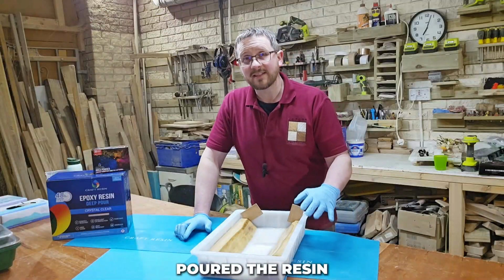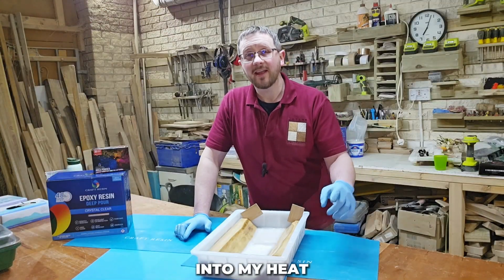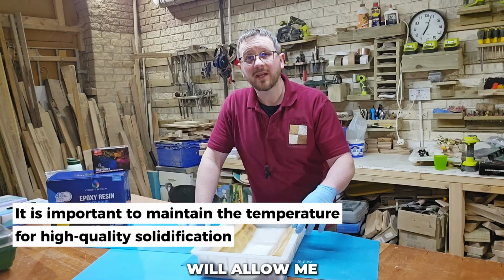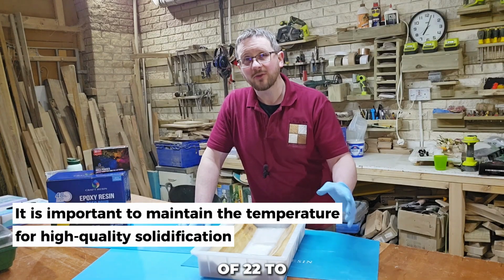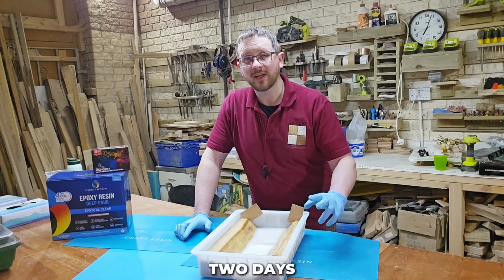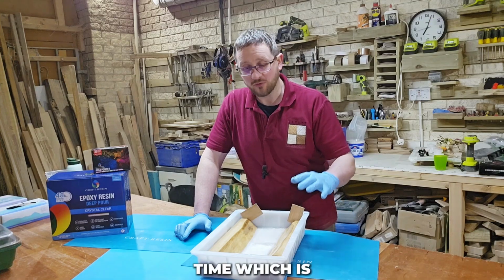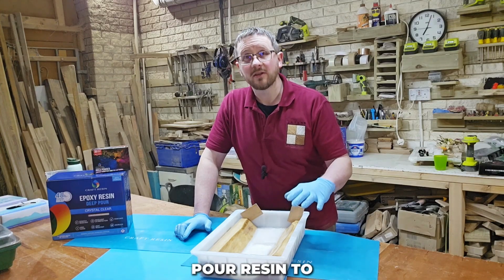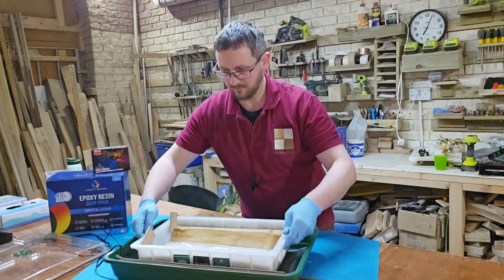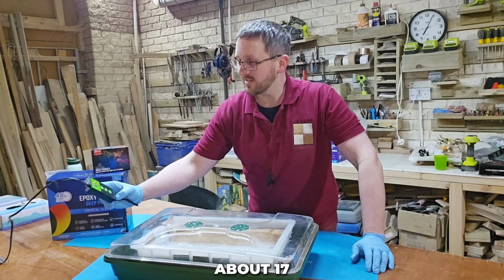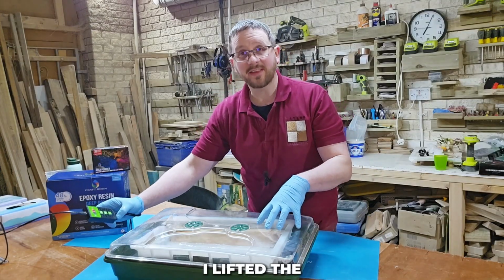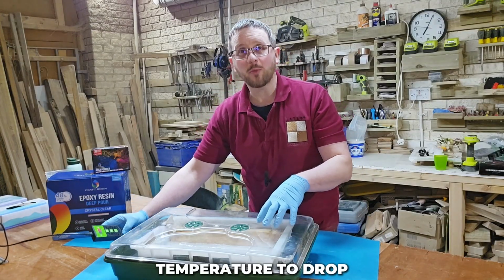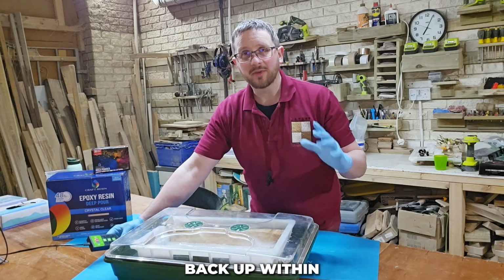Now that we've poured the resin into the tray, it's time to move the tray into my heat tank. The heat tank will allow me to maintain the temperature of 22 to 24 degrees for 2 days, which is the time required for the deep pour resin to fully cure. The tank's sitting at about 17 to 18 degrees because I lifted the lid off. It's allowed the temperature to drop a wee bit, but it'll climb back up within a few minutes.